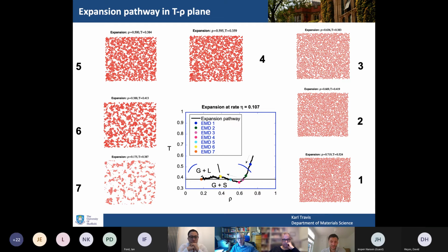So the way I did that is by taking an equilibrated box of fluid, expanding it at one particular rate, I think it was the same rate, 0.1, and then following an expansion pathway through the phase diagram. So the black curve is the expansion pathway. The blue curves there represent the best I knew at that time in history of the liquid-vapor dome in the phase diagrams. This is a T-rho plane.